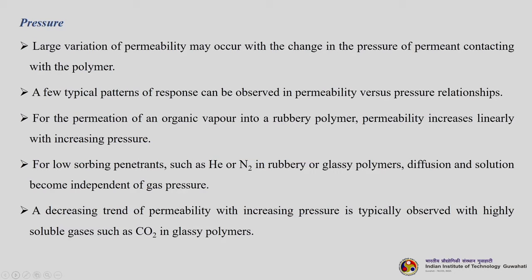Next is pressure. Large variation of permeability may occur with the change in pressure of the permeate contacting the polymer. A few typical patterns of response can be observed in permeability versus pressure relationships. For the permeation of an organic vapor into a rubbery polymer, permeability increases linearly with increasing pressure. For low sorbing penetrants such as helium or nitrogen in rubbery or glassy polymers, diffusion and solution become independent of gas pressure. A decreasing trend of permeability with increasing pressure is typically observed with highly soluble gases such as carbon dioxide in glassy polymers.